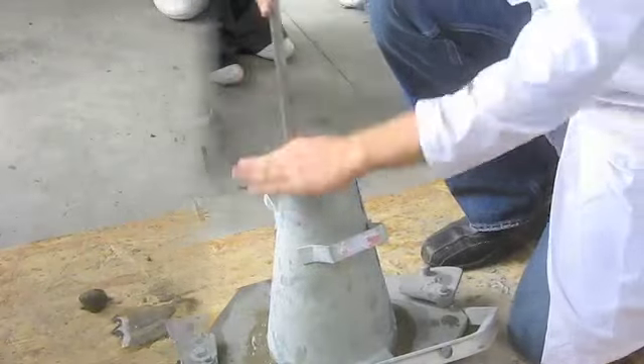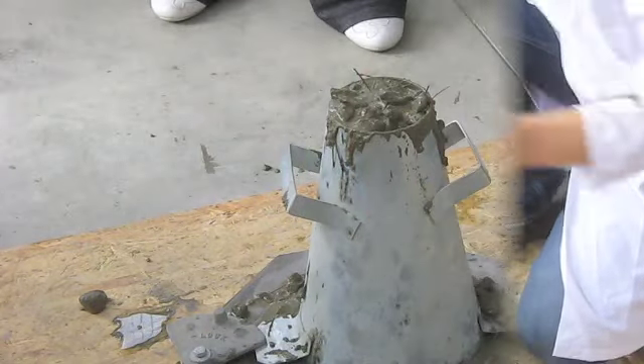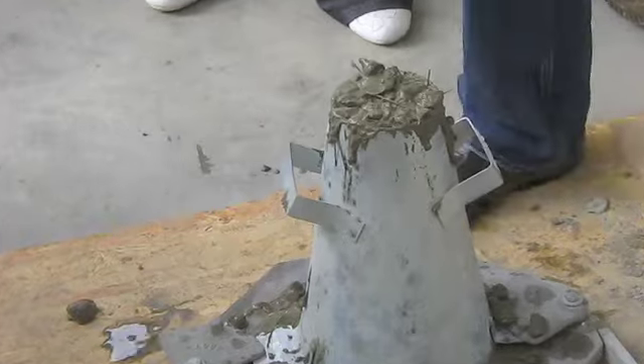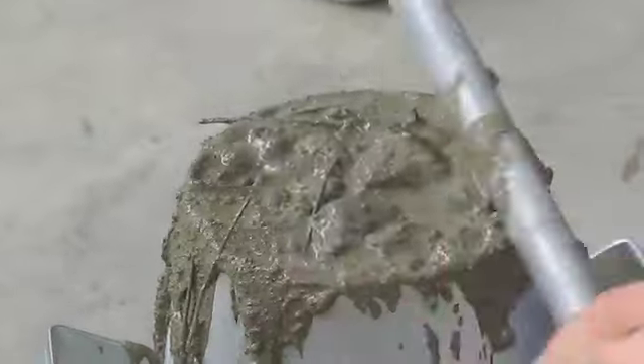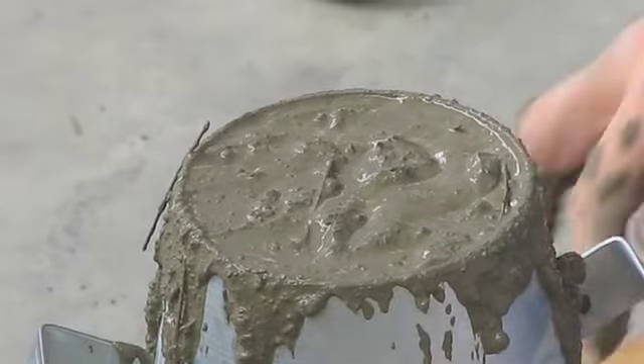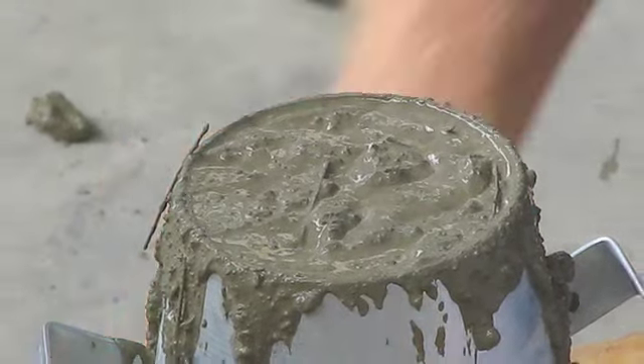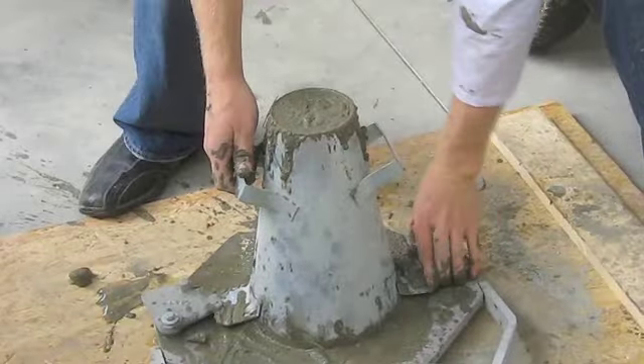You want to make sure that you only penetrate 25 millimeters into the layer below. For the final lift, make sure that you fill it a little bit above and again tamp 25 times. When completed, take the rod and screed off the top layer.